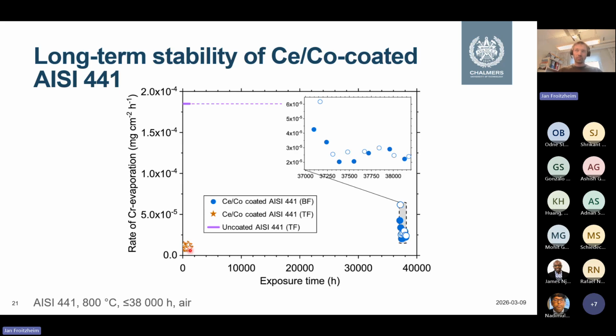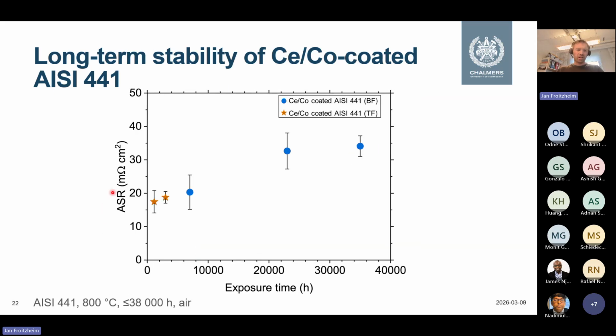As the interconnect is part of the electric circuit, it's also important to keep the resistance of the coating in mind. We could coat with alumina, for example, and the corrosion resistance would be fantastic, chrome evaporation would be no problem, but the resistance would be way too high. Here's the area-specific resistance as a function of time, slowly increasing, roughly following the same parabolic kinetics we've seen before, but 35 milliohms after 40,000 hours is considered an extremely good value.